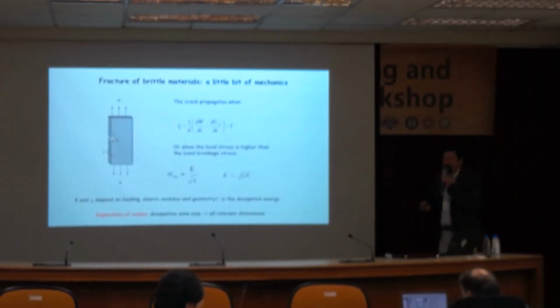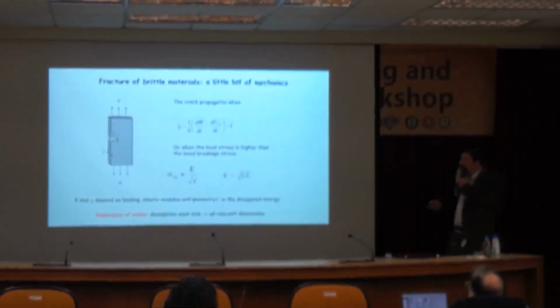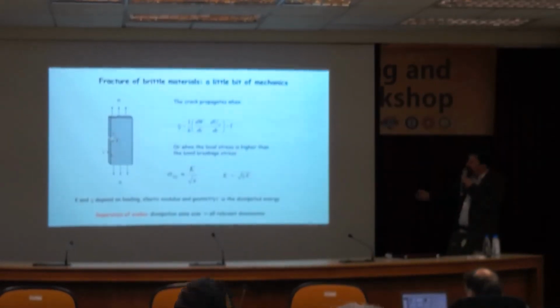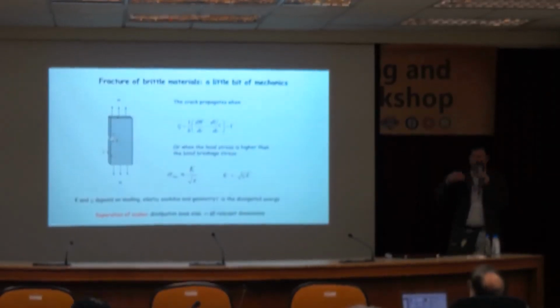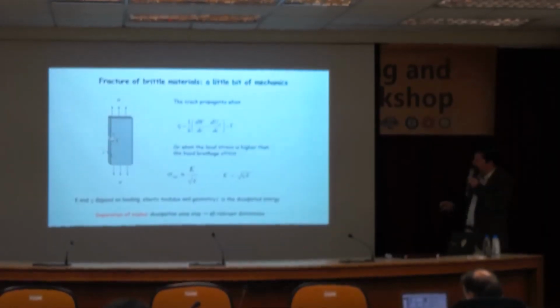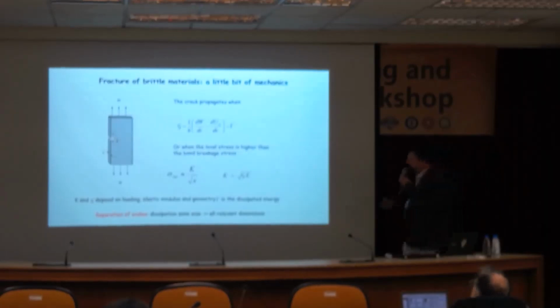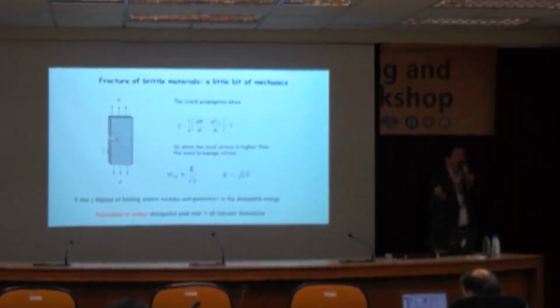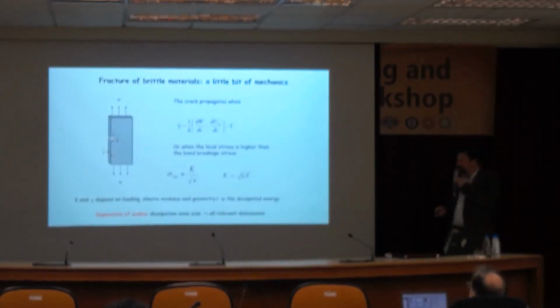And you have two criteria that are actually equivalent for linear elastic material. One is that of a local stress, given by the stress intensity factor K, and it varies as a function of distance from the crack. When the stress gets too high, you break chemical bonds, and the material breaks. And you also have an energy criterion. When you have enough strain energy around the crack, then the stresses are high too, and the crack propagates. For linear elastic material, these two critical values are connected, so essentially the energy or stress criterion gives you the same result.